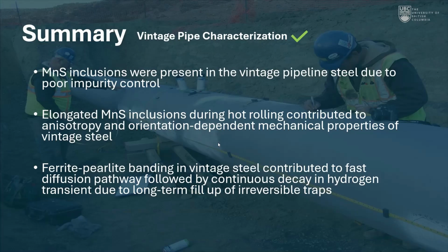time. Okay, so a very quick summary: we've looked at the presence of inclusions and how it corresponds to anisotropic mechanical properties, as well as the hydrogen transients, where initially the morphology of inclusions as well as microstructure can contribute to fast diffusion pathways, but then over time can act as deep sinks for hydrogen accumulation.